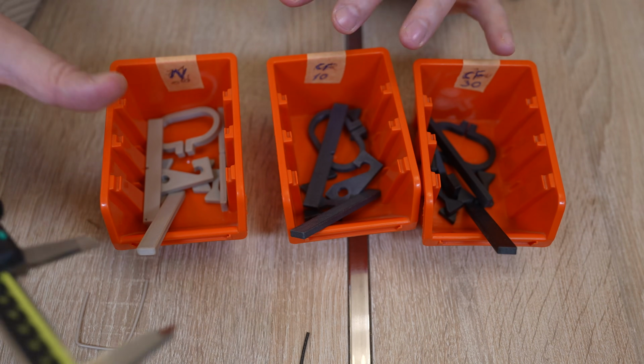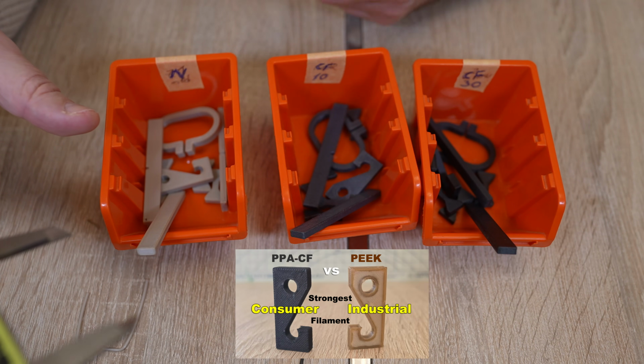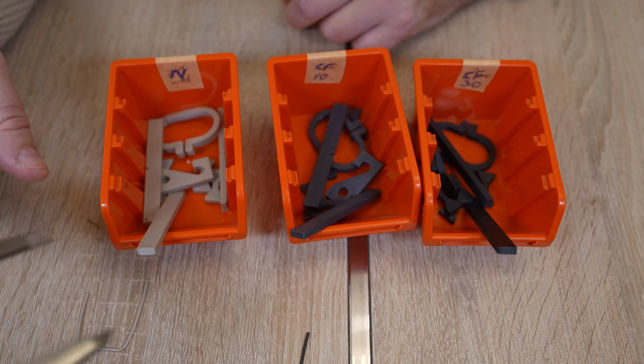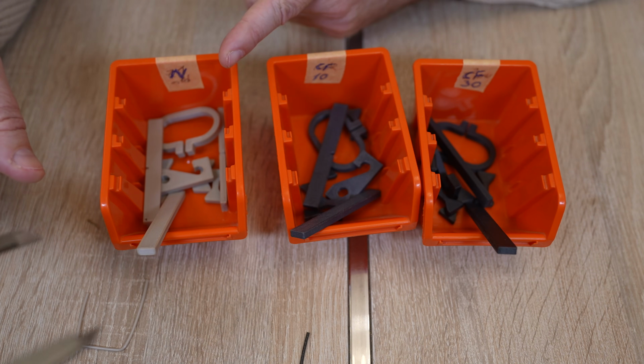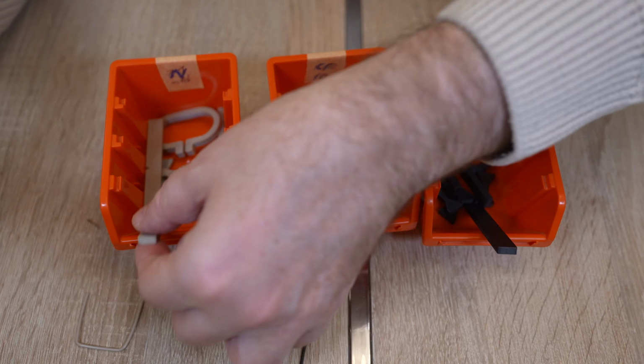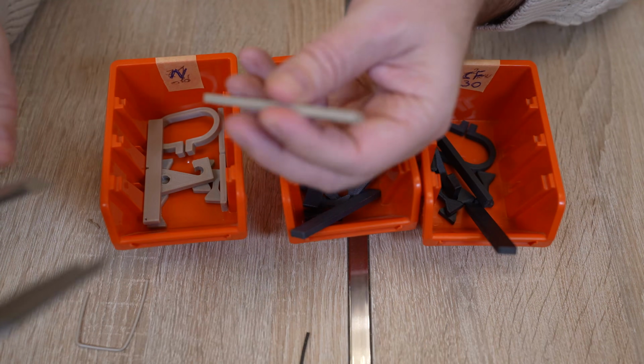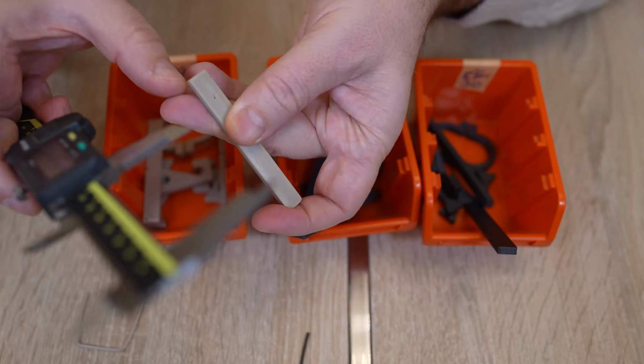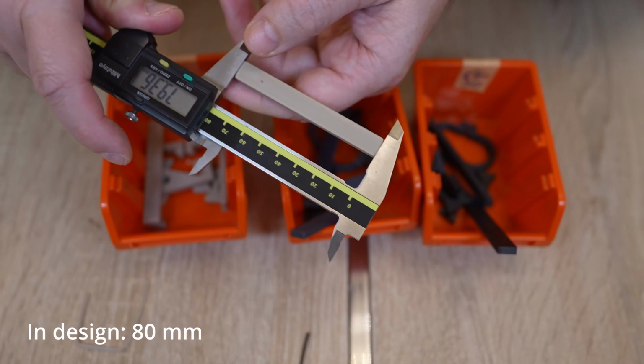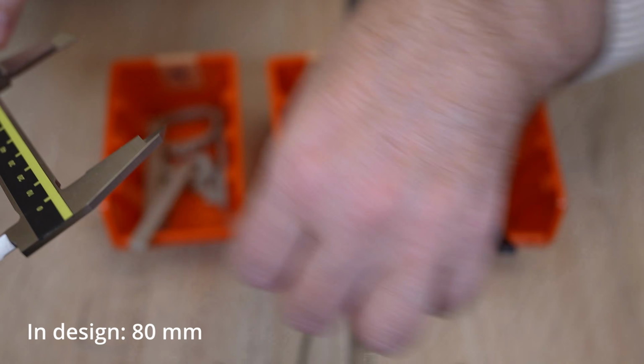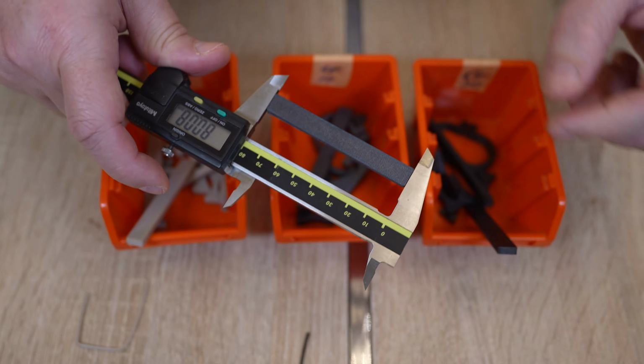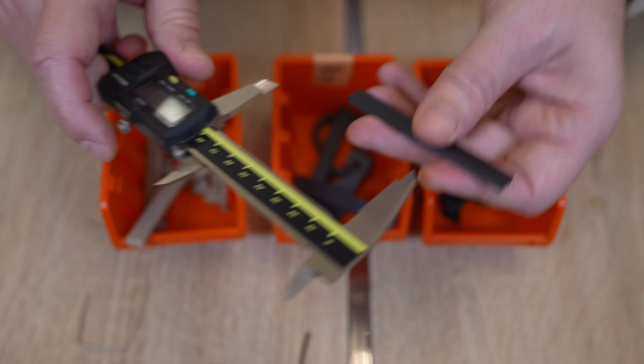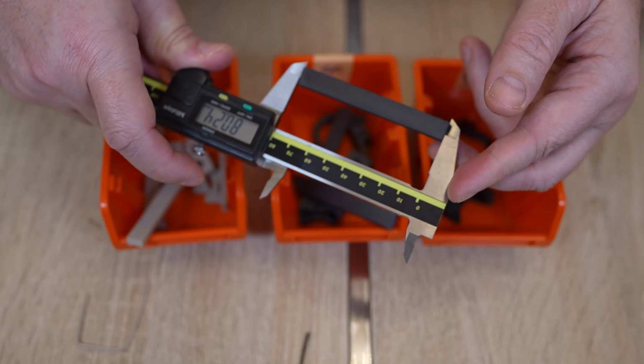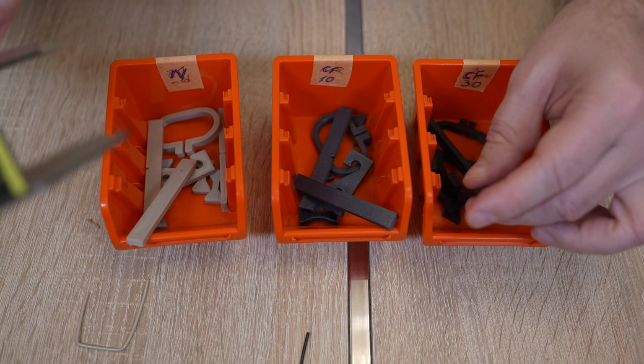These are exactly the same test objects as in that PEEK versus PPS-CF video, printed with 3 walls and 100% infill. Let's check the shrinking. This test object is for the bending test, and I'm measuring above the elephant foot, but basically they don't have an elephant foot. 79.36. 80.08. 80.24, a little bit bigger, interesting.